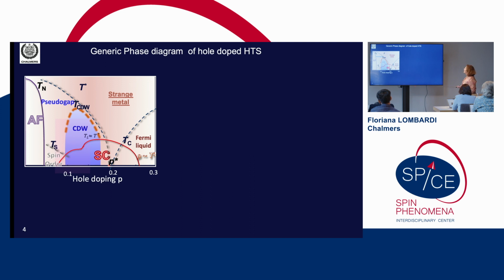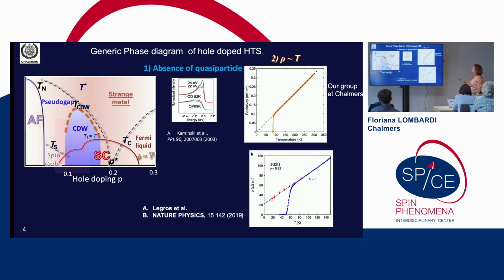hear more from Silke. So, as I said before, the normal state corresponding to this doping is what is called a strange metal. And which are the properties? You are missing quasi-particles, so if you make ARPES, you don't see the quasi-particle peak. And the most striking one is the T-linear dependence over three orders of magnitude in temperature range. And you can see that the extrapolation of this linear behavior goes to zero. This is really, really anomalous. And if you apply a magnetic field to suppress superconductivity, you continue to observe this T-linear behavior. So it is something extremely robust.